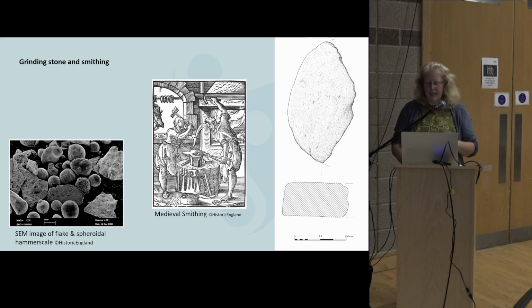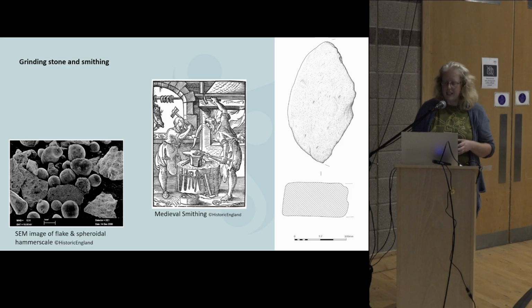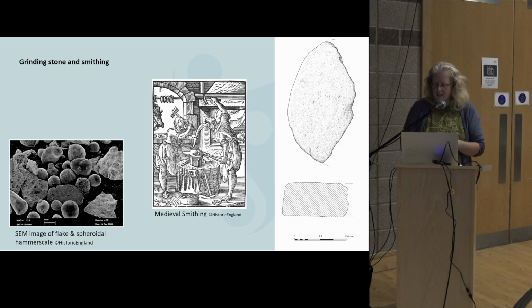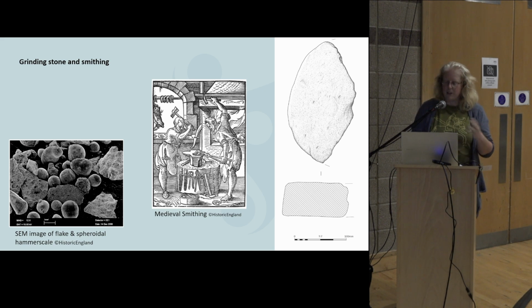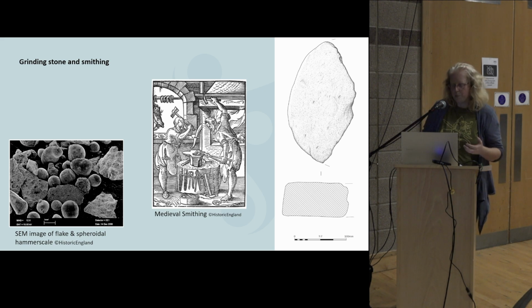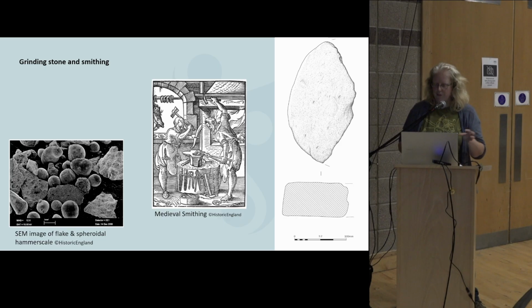Evidence for metalworking taking place on the site was quite limited, but we did have some evidence present in the form of small industrial waste fragments of slag and hearth lining, and several small hearths were identified near to the medieval pits and dated to the medieval period themselves, the 13th, 14th century, which had hearth lining and fragments of hammer scale and slag spheres, which indicates we have in situ smithing activity taking place on this part of the site.